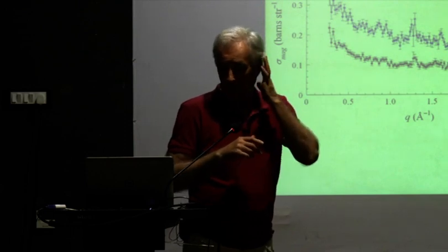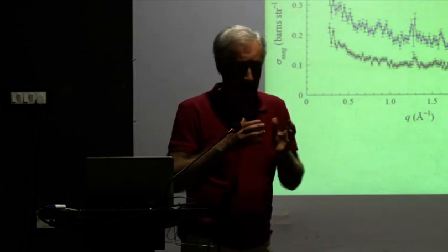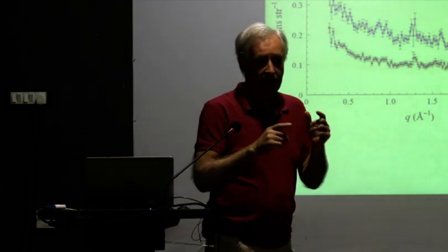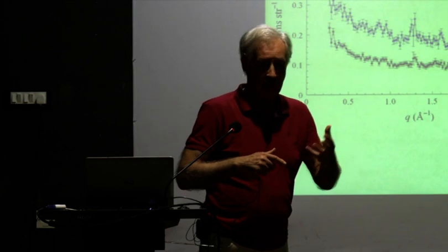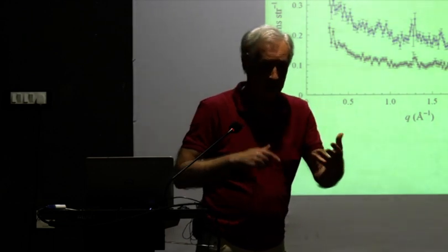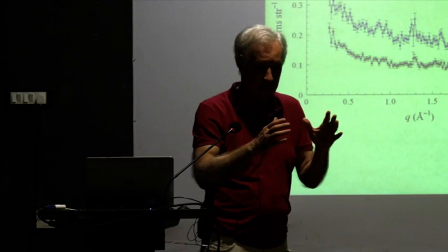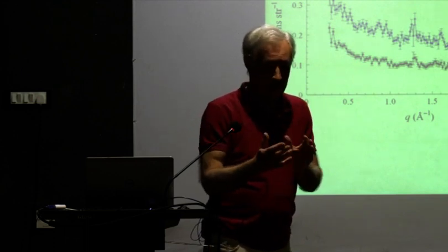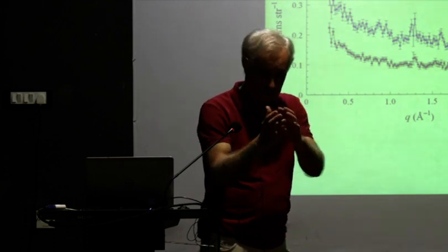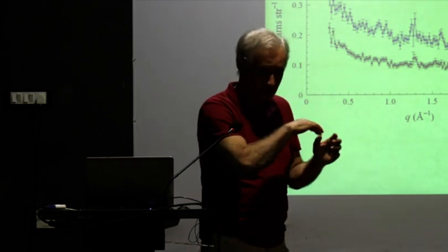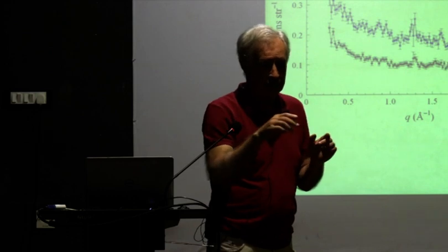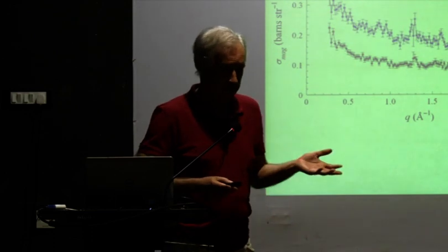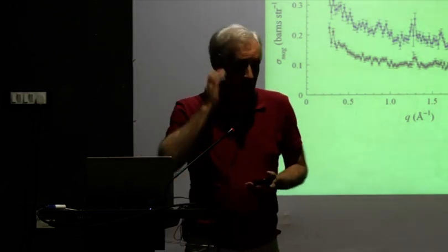so that arranging an antiferromagnetic configuration in such structures would not be that trivial. And even if you had certain configurations, that may not be the only possible configuration. You can have an infinite number of configurations or a large number of configurations, so that you would call this something like a frustrated antiferromagnet with different ground states. And that would give rise to the broadening that we are seeing here. Okay?